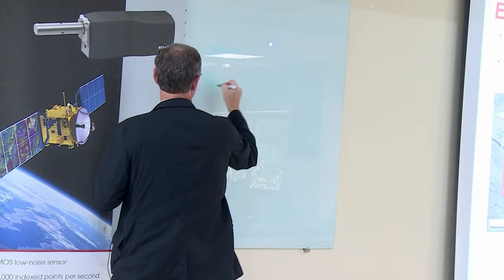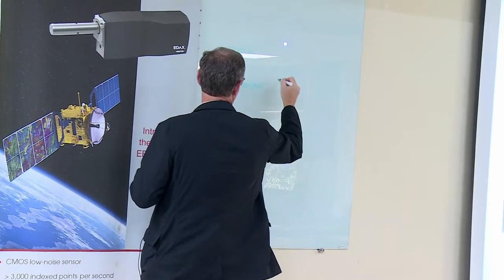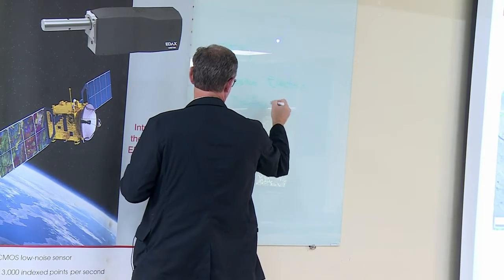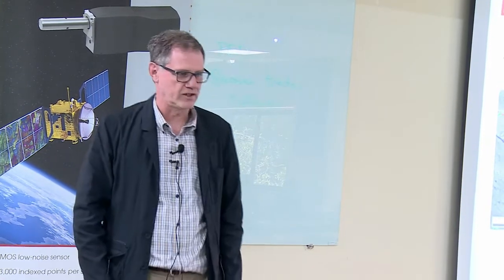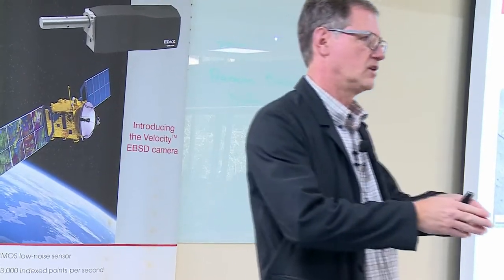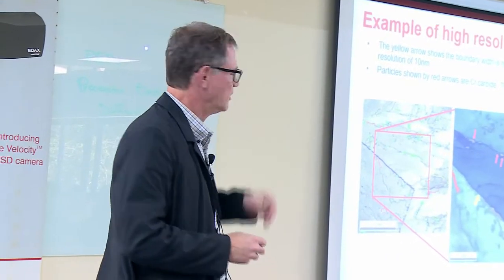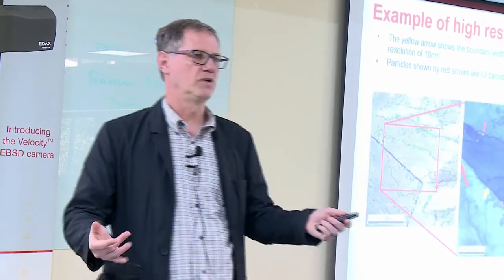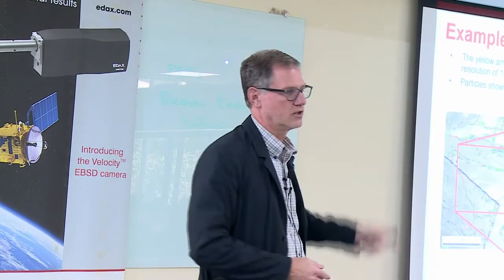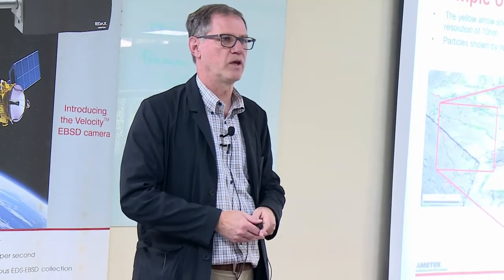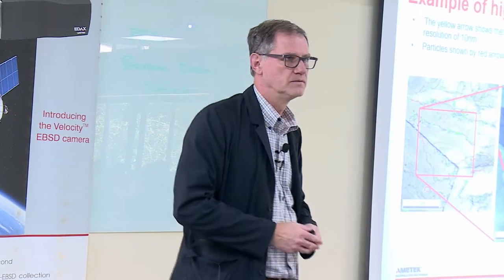So if you look up ASTAR or precession, the technique in the literature is called PED, precession electron diffraction. And so they have some hardware in there to increase the solid angle. If you just did straight spot patterns, you don't sample enough of reciprocal space to really get a good indexing. But with the precession technique, you're able to get enough spots to be able to index it. And that's the name of that technique. So if you're interested in that, I can point you in the right direction and give you some papers. But that's not something we do.